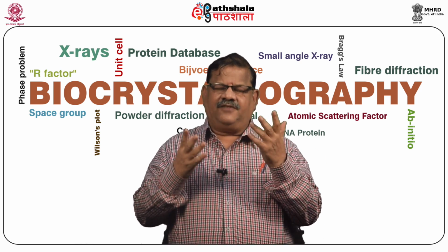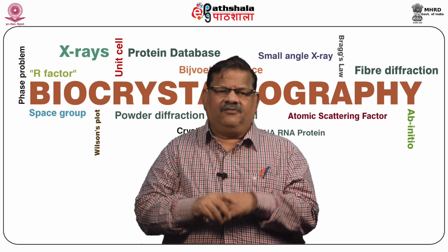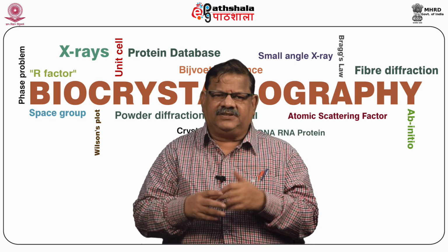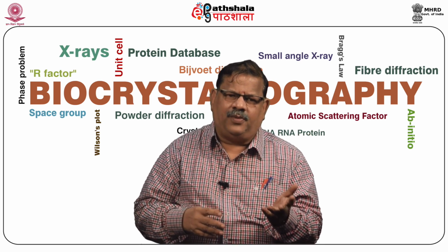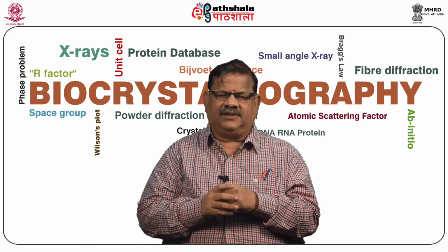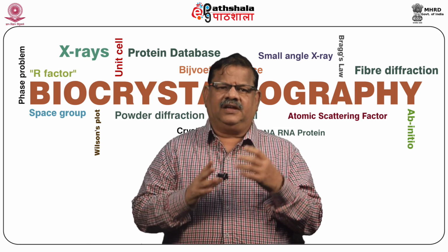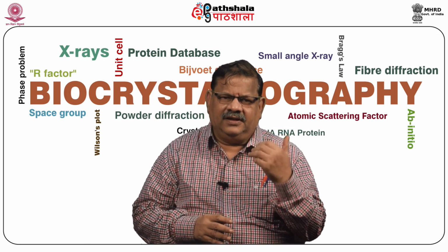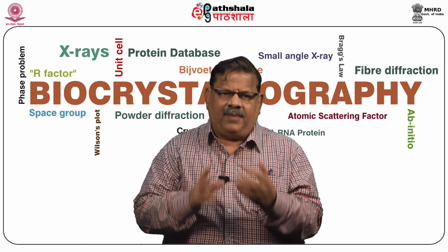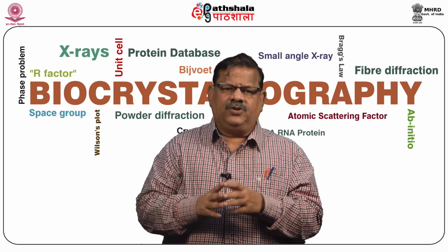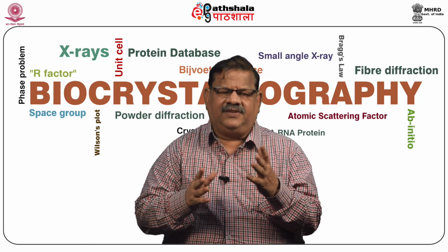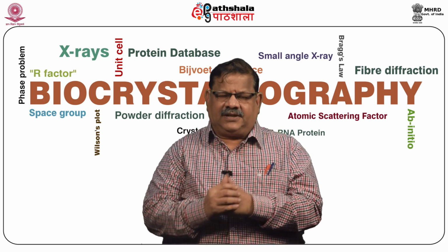This is done in the case of multiple wavelength anomalous diffraction, where you collect the data at the peak wavelength, the inflection wavelength point, and at the remote point, where we talk about a huge change in the real part of the atomic scattering factor when you collect the data between the remote wavelength and the inflection point wavelength. But nowadays people use single wavelength anomalous diffraction data, where with just the anomalous difference Patterson we can locate the position of the heavy atom.